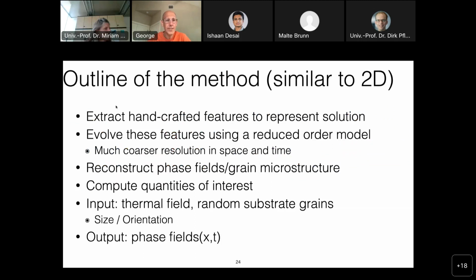Similar to 2D, we're going to extract handcrafted features to represent the solution. We're going to evolve these features using a reduced order model and neural network. We're going to reconstruct the phase field and the grain microstructure from these reduced features, and then we can compute quantities of interest. The input will be the thermal field that comes from the heat equation solver, the random distribution of the substrate grains, and the output will be the phase field for every grain as a function of space and time.